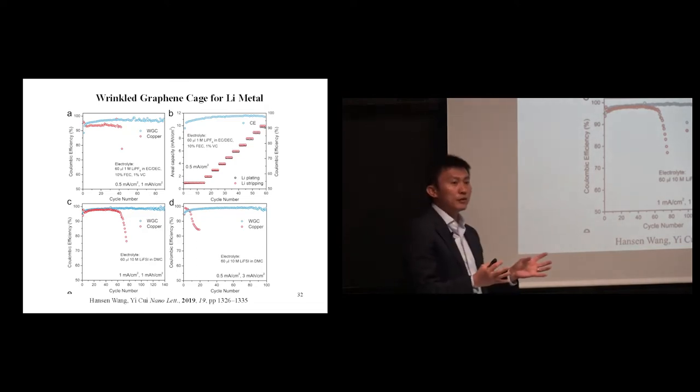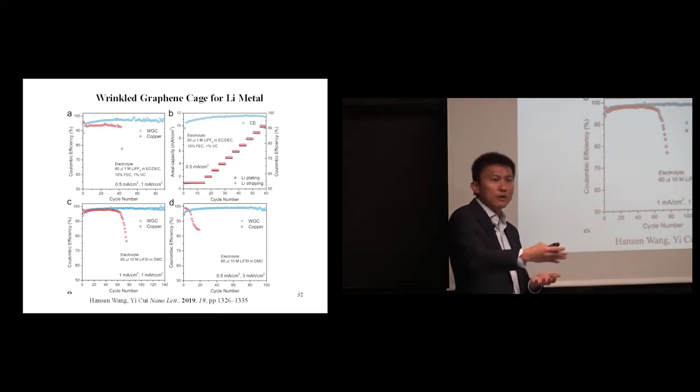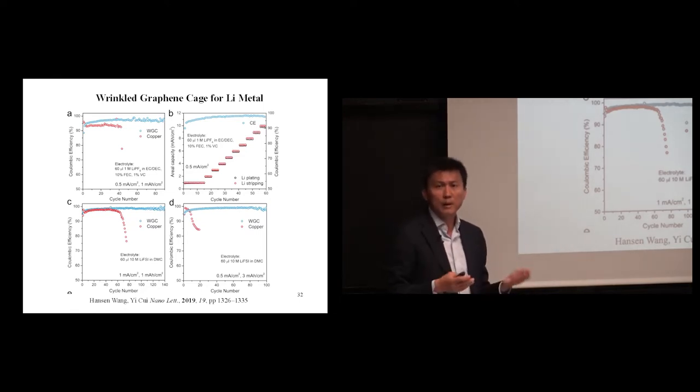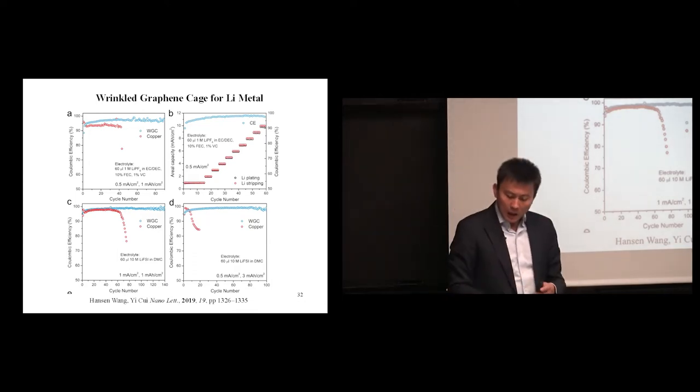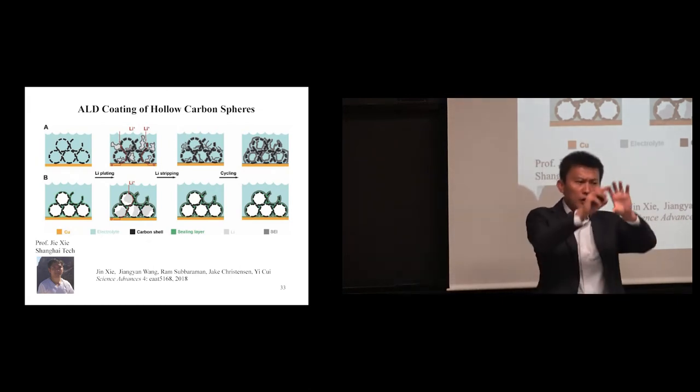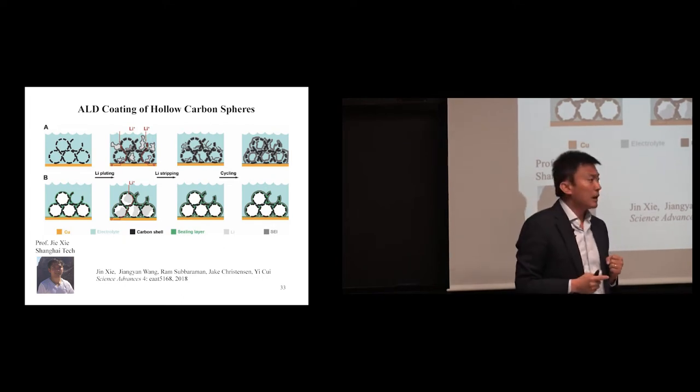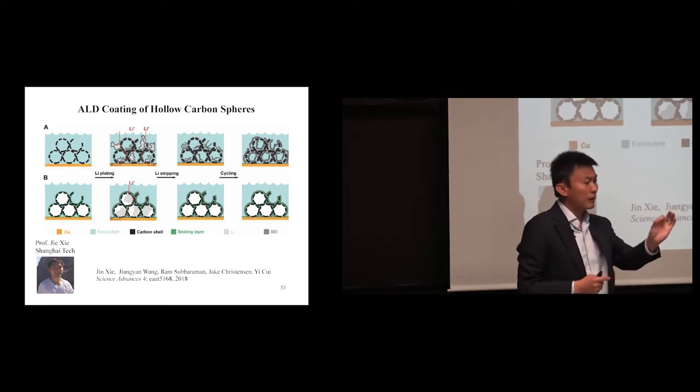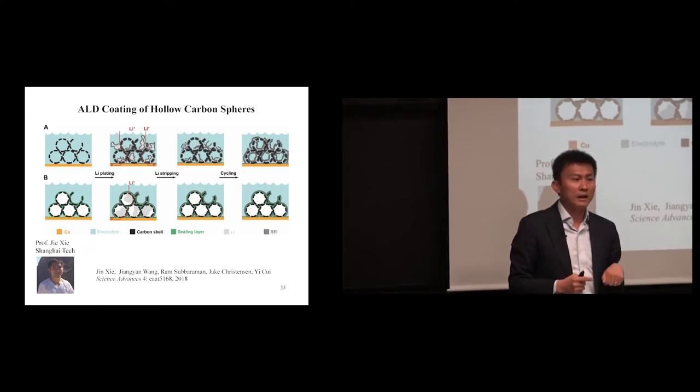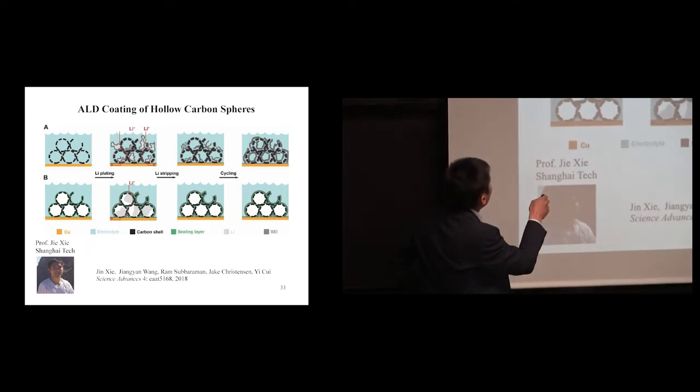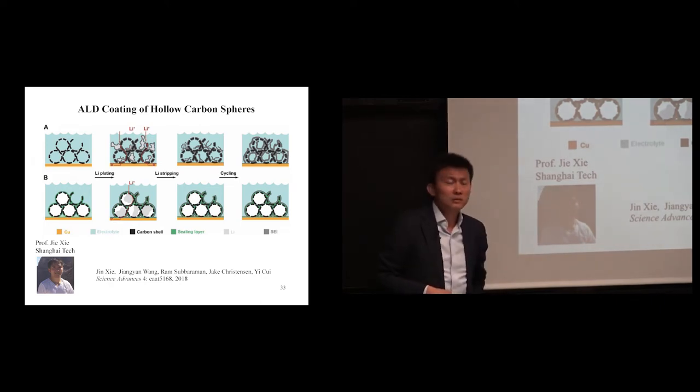So with this understanding, then we ask the question, is this amorphous carbon the best? What about you turn amorphous carbon become graphitic? So we can grow graphite layer. The reason graphitic carbon is good, the graphitic carbon is very resilient mechanically. If you have amorphous carbon hollow sphere, you press on it, it can break so easily. Now with graphitic carbon, you can press on it. It will be still stable. Mechanically, that's a good thing. When you build a battery, you, anode and cathode and separator need to press together. So now with this, we plate lithium in there. This is an empty one. If you cut the cross section, you can see it. You plate lithium in there, you can see lithium filling the space inside this graphitic carbon. What's surprising to us is my students keep plating this beyond 5 milliamp-hours, go to 10 milliamp-hours per centimeter squared. It deposits so much more lithium metal. And this interior space cannot hold. And then it will start to grow out. But to our surprise, this lithium plating forming this cross section-wise, very dense layer right there. We don't see the dendritic growth. I was expecting if you have plating outside, you are going to see lithium dendrite. But somehow we don't see that.